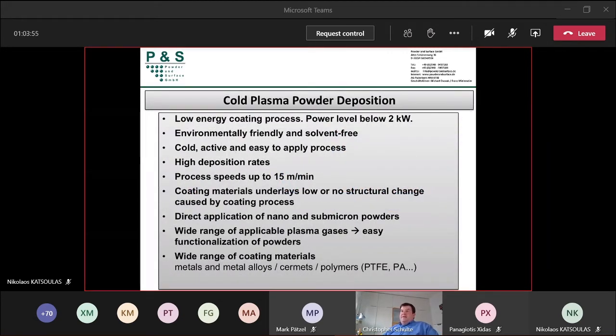Okay, next page, please. So in conclusion, here are the main advantages or the main points of the CTPD. The low energy, and then environmentally friendly and solvent free, because there's no need for additional adhesives or solvents. It's a cold, active and easy to apply process. The deposition rate is normally high. Process speed is up to 15 meters per minute. This is a point we discuss later in this presentation. There is no structural change of the coating materials caused by the coating process. That is what I mentioned before, because of the low temperature we established in the substrate.